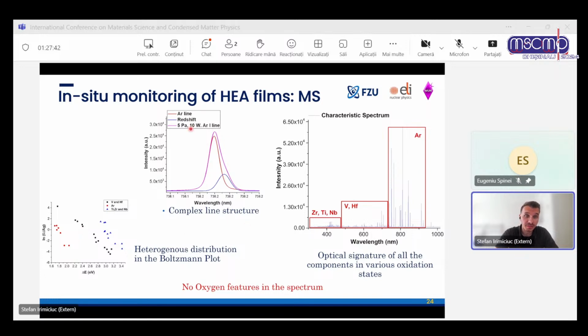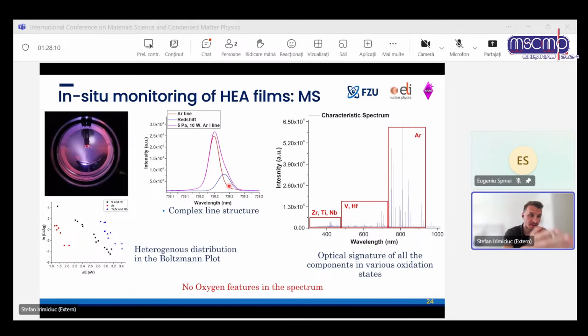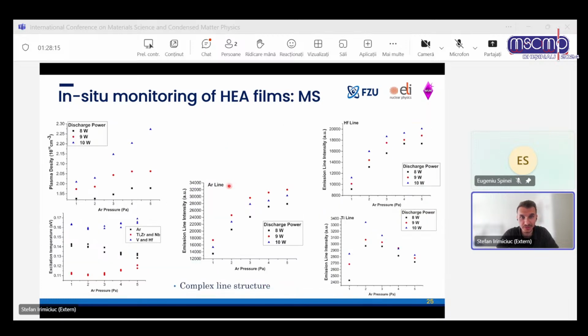And the most intriguing one is that there's a red shift in the emission spectroscopy of the argon line, which means the particles are slowed down during the expansion. But more importantly, there's no oxygen during the deposition. So all the trouble that we might have with the oxidation of the film doesn't occur during the deposition. And I think that's an important thing to have, and proof that we actually did the plasma and we recorded it.